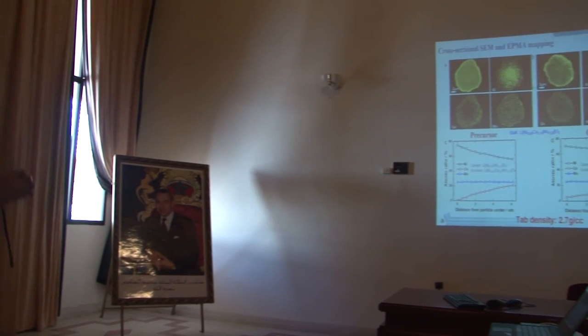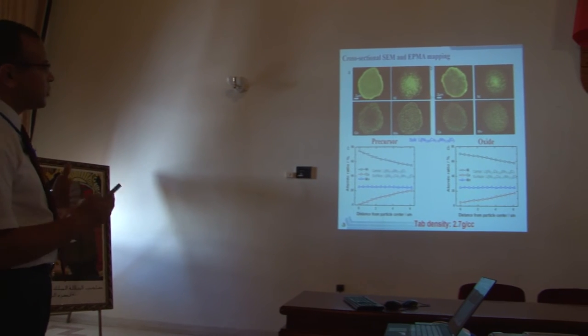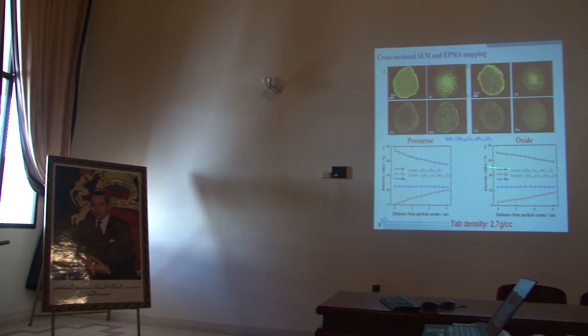This is the SEM and EPMA of this material before, during the hydroxide process and after. So the material doesn't change morphology. Once you form the spherical particle at the hydroxide, you calcine them. You may end up with some interdiffusion of the metals, but you see clearly that the gradient is maintained in this case.